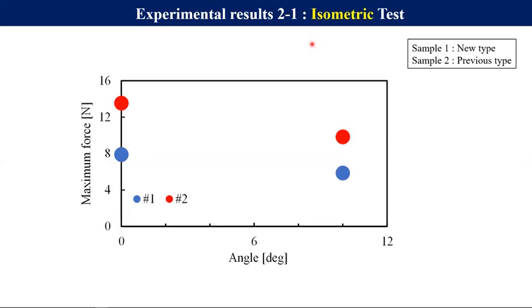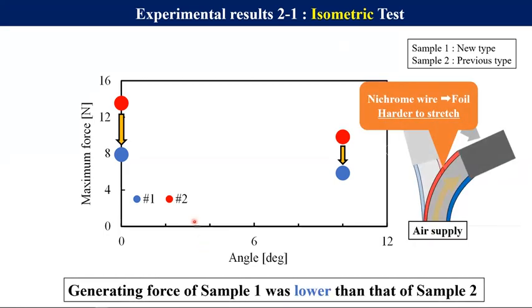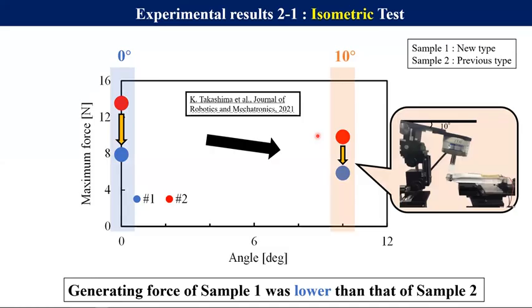This is the experimental result of the isometric test. And the vertical axis of this graph shows the maximum force, and the horizontal axis shows the bending angle. And first, I'd like to draw your attention to the comparison of each sample. As you can see, the generated force for sample 1 was lower than sample 2. And this result was also attributed to the change from Nichrome wire to foil, which increased the tensile elastic modulus. In addition, similar to the results of the previous study, both samples showed a decrease in force after the bending compared to the force before the bending.